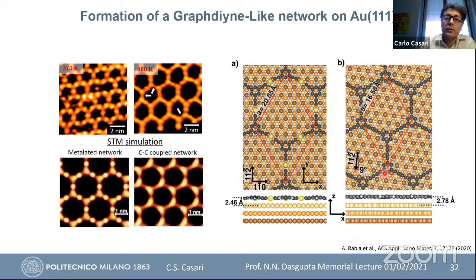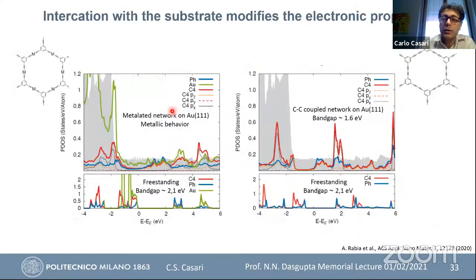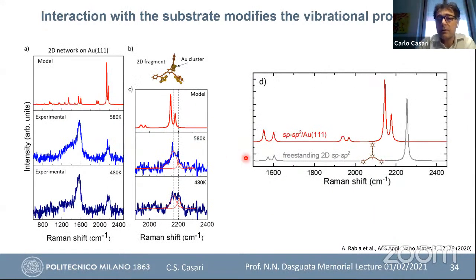By comparing theoretical simulations with what we observe, this is the metal organic system, while in this case we have something moving towards the homocoupled network. In the theoretical simulation, this is very interesting because the system is affected by the presence of gold, and so with respect to the freestanding system, you have a change of the band gap or a metallic behavior. So again, the presence of gold can be used to tune the properties of this kind of materials. This is also reflected in the vibrational properties.